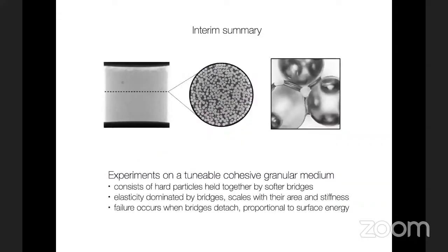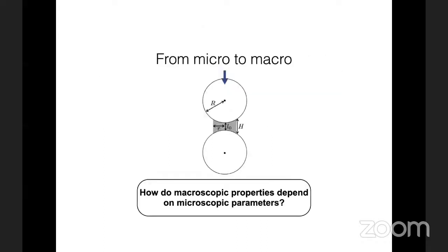Okay, so this is a summary of the experimental side of things. We've made a tunable cohesive granular material. This consists of hard particles held together by softer bridges. And the elasticity of this is dominated by the bridges and scales with the cross-sectional area and the stiffness of the material made of those bridges. And we have failure occurring, which we can relate to a fracture energy. And that fracture energy is the energy it takes to peel the bridges off of the particles.